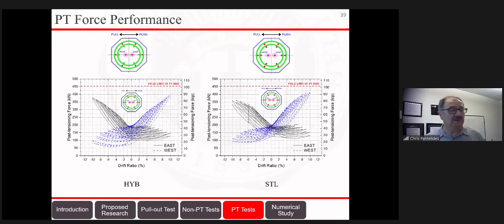So what happened to the post-tensioning force? I showed you the load cells that were used to measure this force at all time. And you can see that we're starting here in the middle at 0%, and then we're moving. And you can see this typical butterfly shape. As we increase the drift, of course, the force in the post-tensioning bars becomes higher. But the key number is that this red line is the yield limit of the post-tensioning bars. And you can see that in both the hybrid on the left and the steel on the right, we were able to stay below that number. The hybrid reached about 88% of the yield limit of these bars, and the steel reached about 91%. So both of these performed very well, and they did the job we wanted them to do.